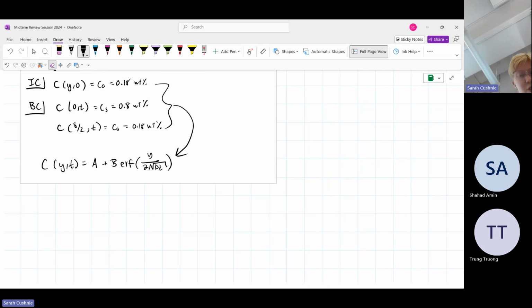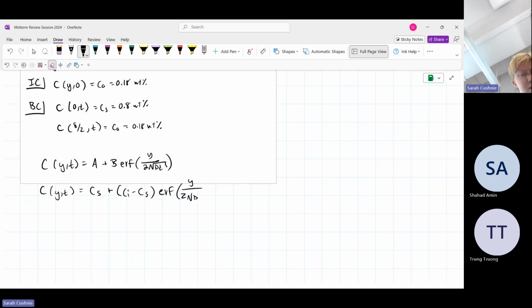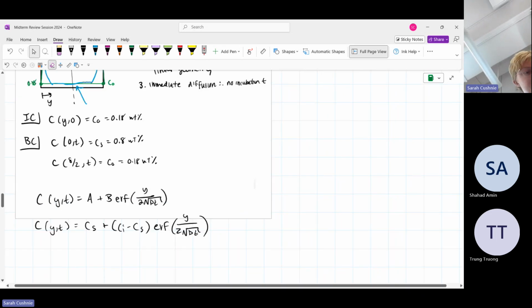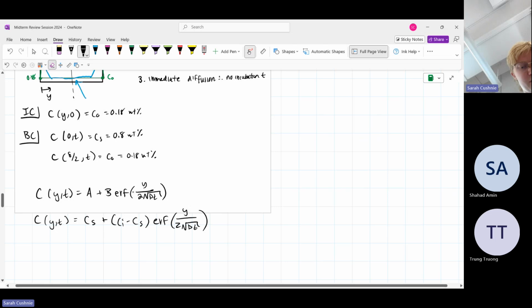We can just take a shortcut and write that C at y of t is equal to CS, the surface concentration, plus the difference between them, so Ci minus CS, times the error function of y over 2 root Dt. So we're going to start by using this equation. Let's see what we know. We know CS. We know Ci minus CS, where Ci is C0. I'll rewrite it using C0 minus CS.